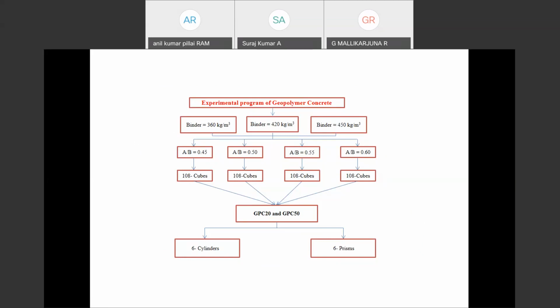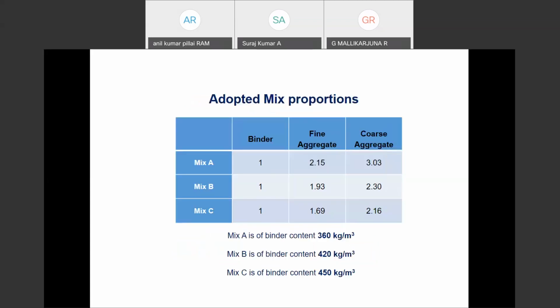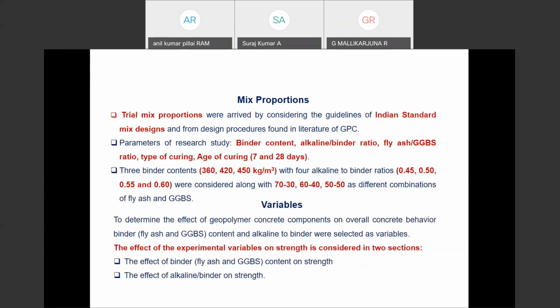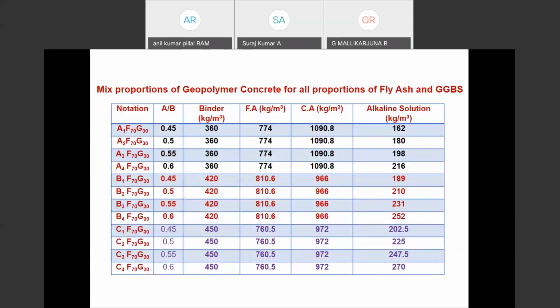And after that, we tested specimens for 20 to 50 MPa for the mechanical properties of flexural strength and split tensile strength. And these are the binder contents we adopted for the mix proportions. The main thing is that in the experimental variables, we have taken different sections: the effect of binder content, that is the fly ash and GGBS content, and the effect of the alkaline to binder ratio. Fly ash and GGBS were varied from 70-30, 60-40, and 50-50, and these were the mixes we considered for preparing our mix proportioning there.